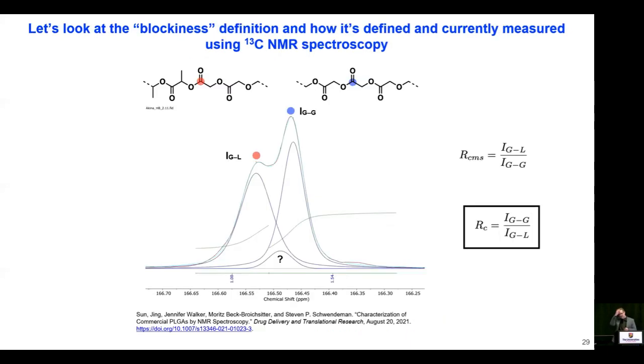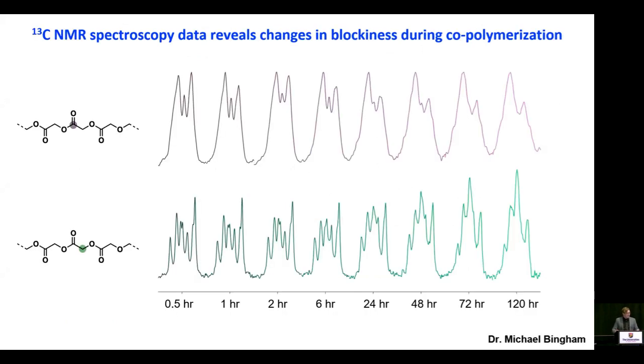And so now this brings us to the blockiness. How this is done currently is one might look at the carbon-13 NMR spectrum of the carbonyl carbon, and you're looking at heterodyads, with the argument here that the more heterodyads you have, the less blocky the material is. And so we looked at that signal there at the top, and so you can see how it varies as a function of time over 120 hours.